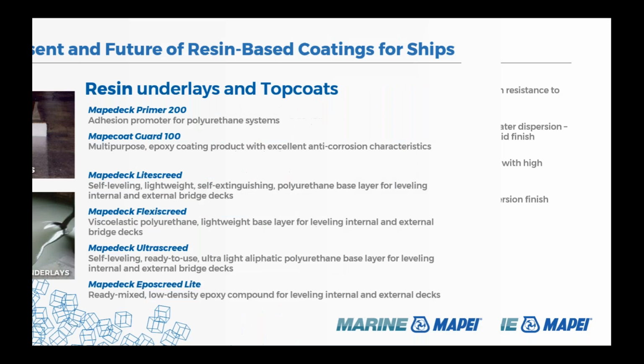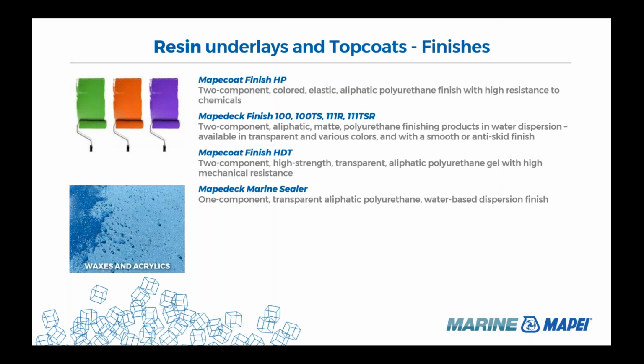Now, the new resin-based coatings also can be enhanced by adding additional finish layers that can seal or color the surface. So you'll see here that we have MAPEcoat Finish HP, MAPEdec Finish 100, 100TS, 111R, and 111TSR, MAPEcoat Finish HDT, and MAPEdec Marine Sealer. In simple terms, the MAPEdec Marine Sealer is a clear coat that we apply over the polyurethane resin-based deck systems, both the MAPEdec Teak design and the MAPEdec design, as a general sealer to make the surface easier to clean. When we get into the MAPEcoat Finish HDT, this is a clear finish typically used to protect the polyurethane resins inside of a pool from chemical attack.